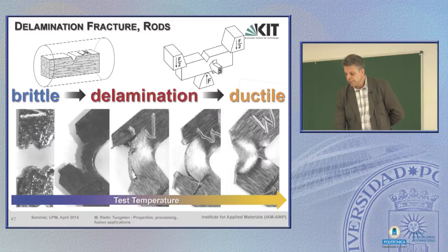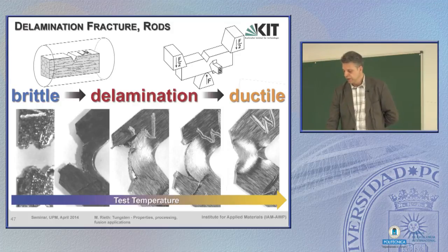Now here, this is what I have called delamination fracture. You see the fracture does not go through the specimen, it develops along the grain boundaries, along the rolling direction, along the elongated grains or platelets. This is very typical of tungsten materials.